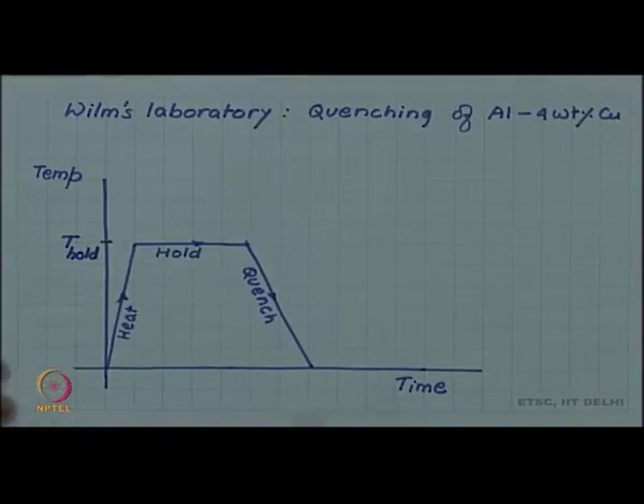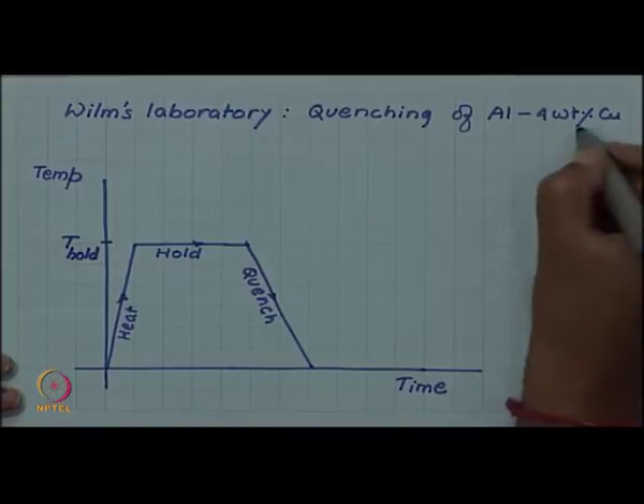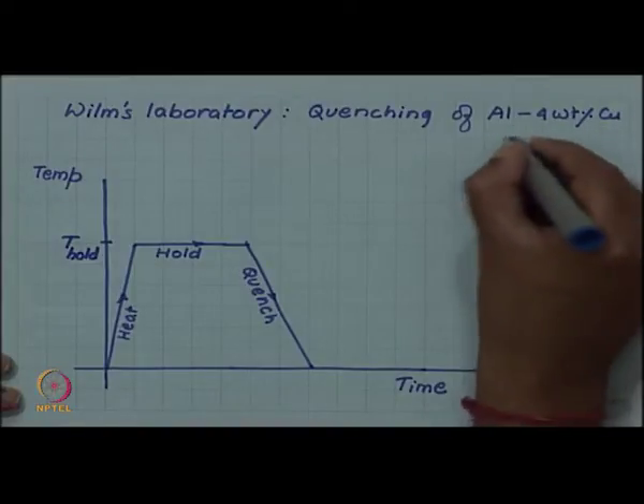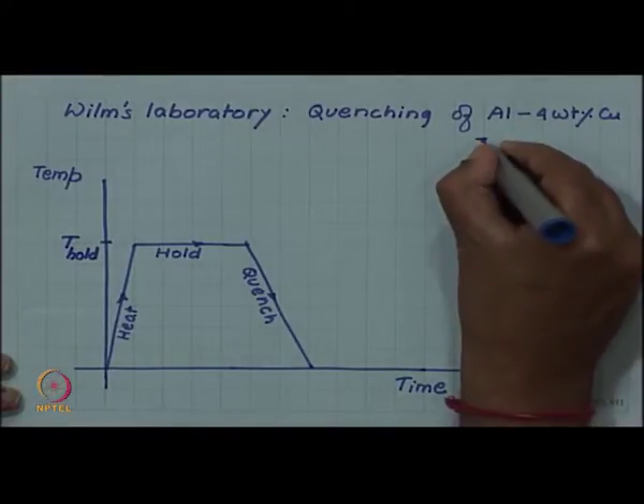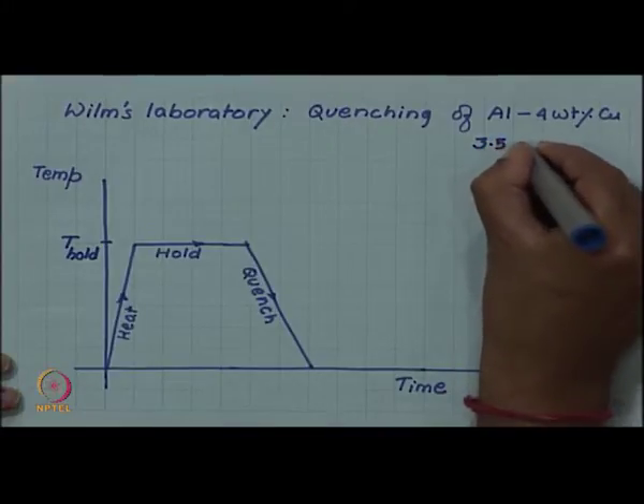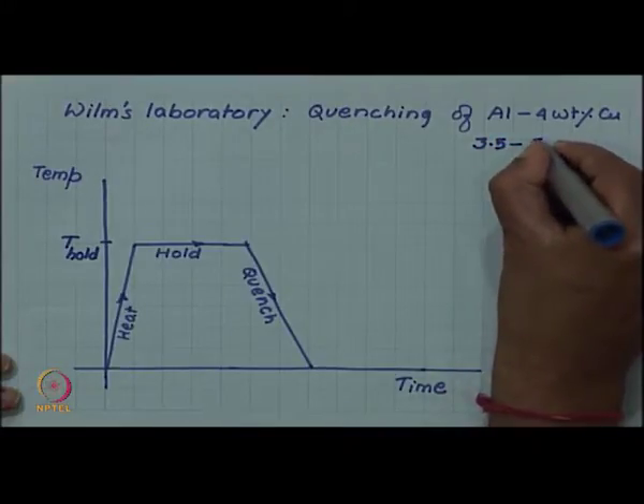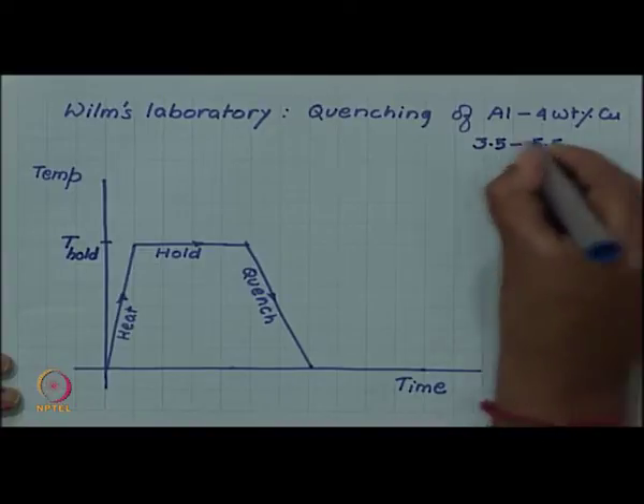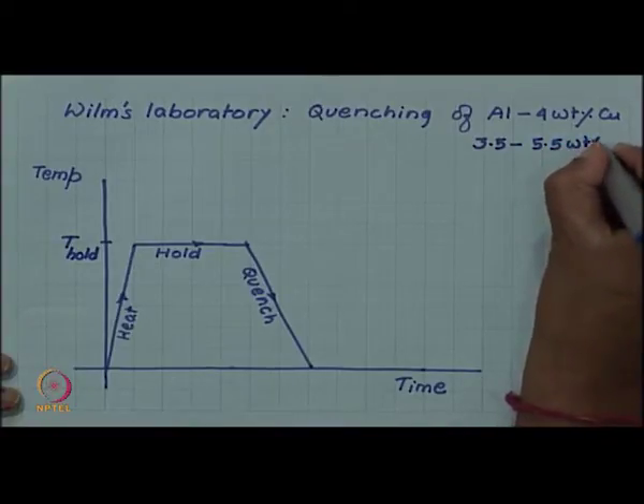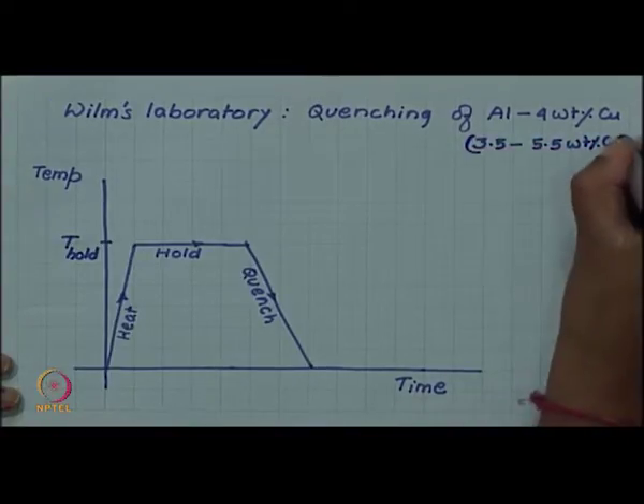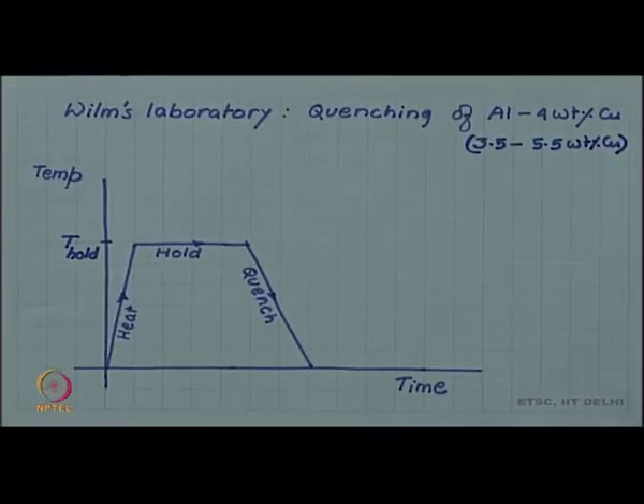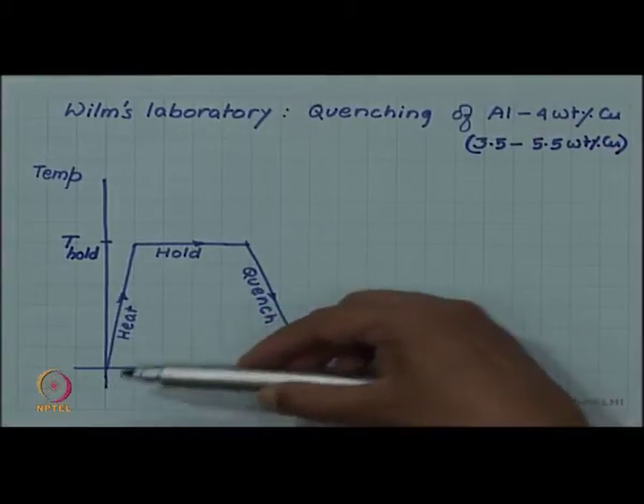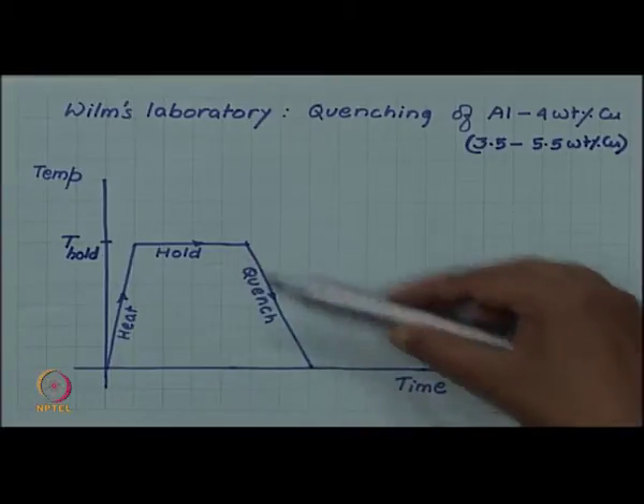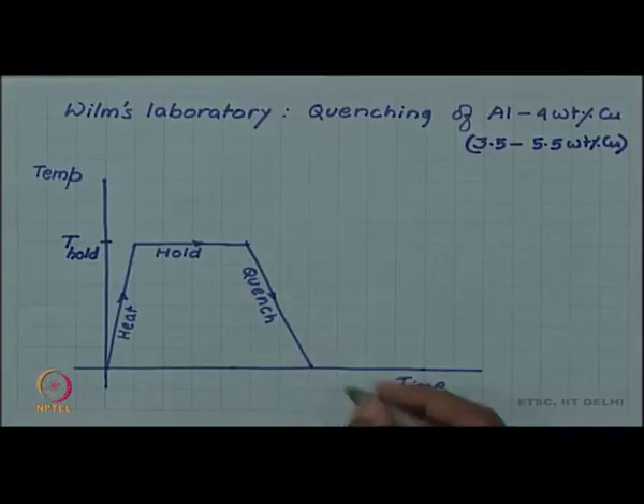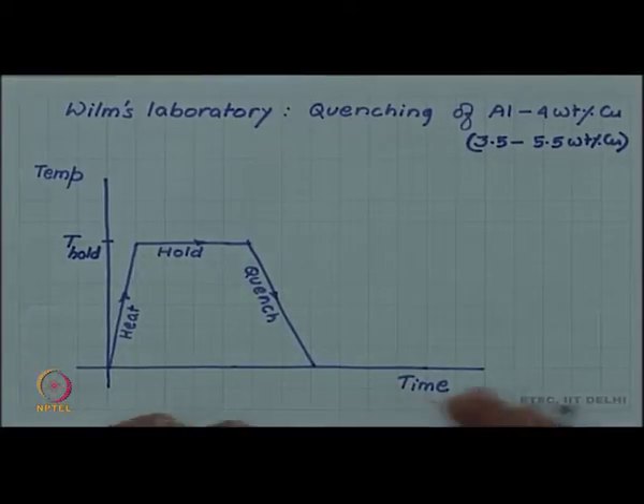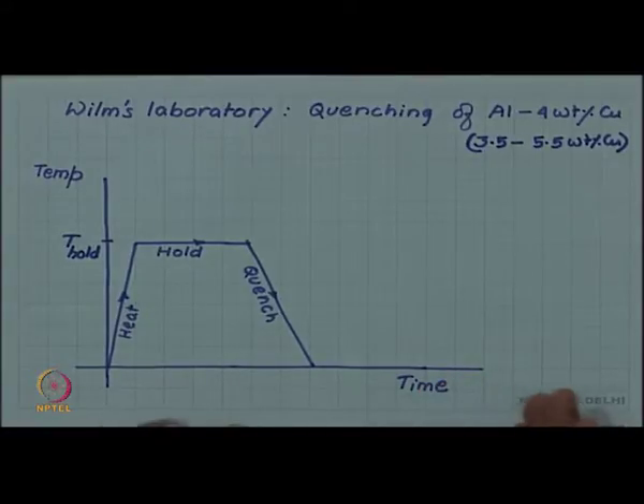So he made a range of aluminium alloys, in particular aluminium 4 weight percent copper alloy. The copper percentage actually he tried from anywhere from 3.5 to 5.5 weight percent copper. So he made several alloys, and then he attempted this heat treatment, heat, hold and quench, and then measure the hardness. However, initially he had no success.